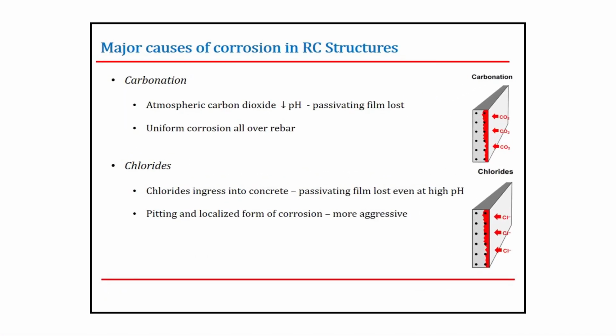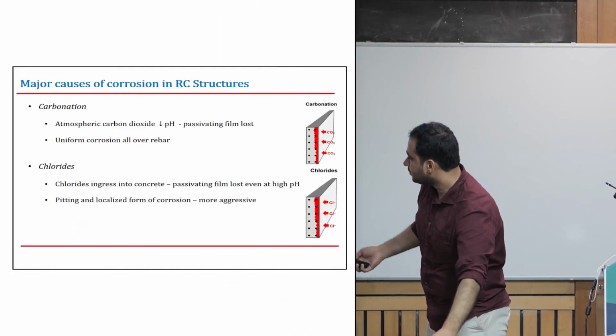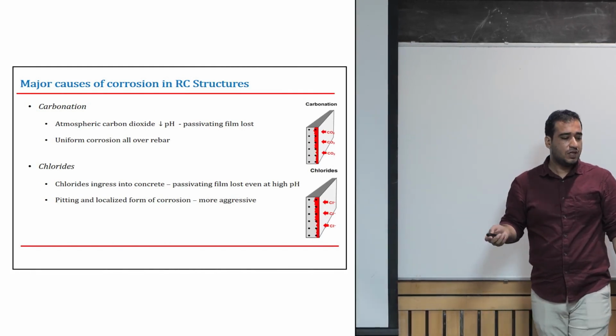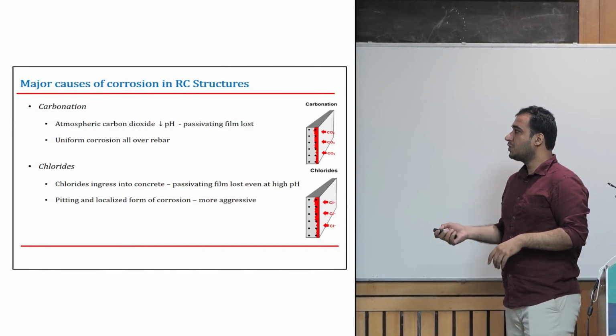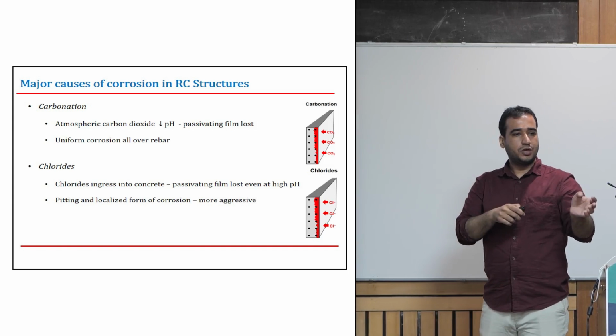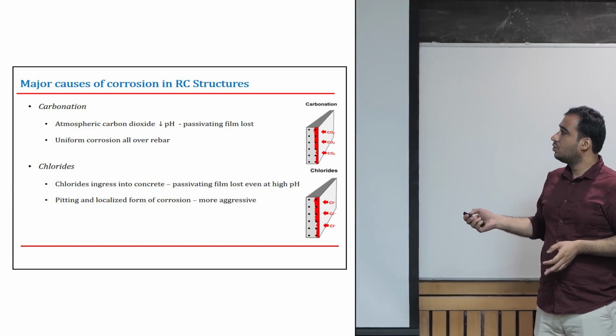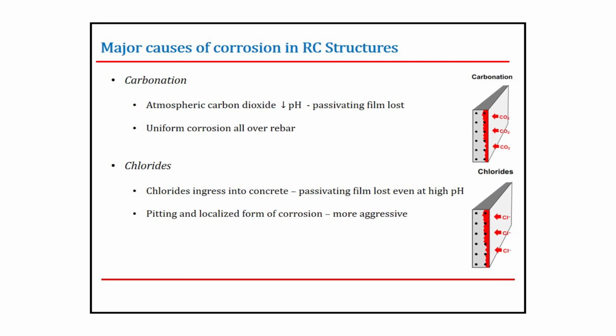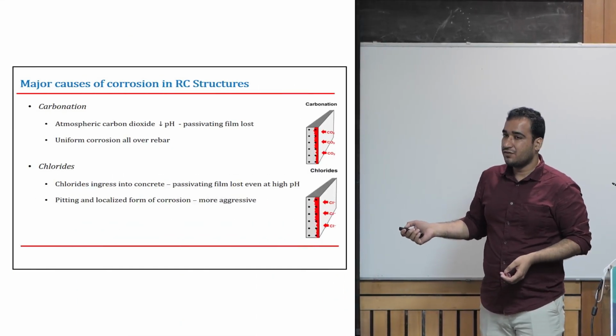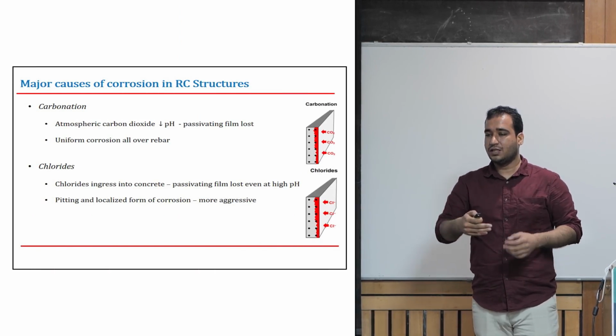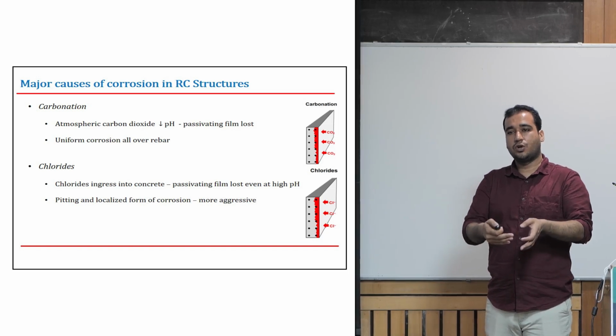Now coming to what I talked about, what are the main causes of corrosion? Often, the main causes of corrosion that we see are carbonation, one of the reasons, and another reason is chlorides. What happens in carbonation is atmospheric carbon dioxide gets into the concrete system and it reduces its pH and you start to lose the passivating film. I showed you that at around 12 only you have a passivating film, but once your pH starts to fall too low, you don't have that passive film anymore protecting you from corrosion. It's destroyed. While in the case of chlorides, chlorides get into the concrete and they locally destroy the passivating film. It's not like carbonation where your whole front is moving. It's just locally, at a point, that the passivating film is lost due to the chlorides being there.